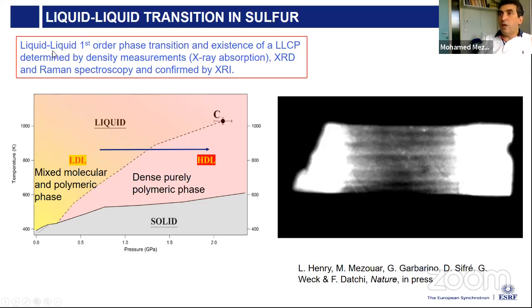We could evidence a liquid-liquid first-order phase transition using density measurement by X-ray absorption. We also confirmed this transition using X-ray diffraction and Raman spectroscopy. And as you can see here, it was also confirmed by X-ray imaging. And I have chosen to show you a little video.